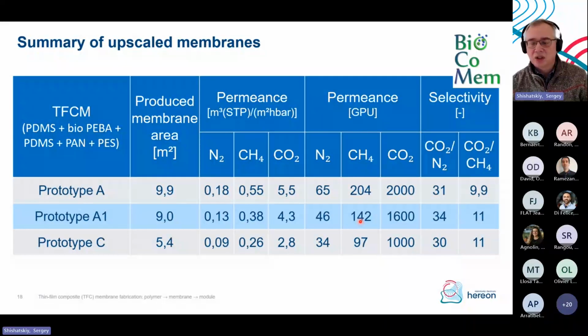And here we see the table of properties of membranes which were produced within the Biocomem project. And you can see that we can have up to 2000 GPU, or about 5.5 cubic meters per square meter hour bar of carbon dioxide with selectivity of 31, 34, 30. Not too high selectivity, I should say, but for the first stage of gas separation, or for the flue gas, that's quite good.